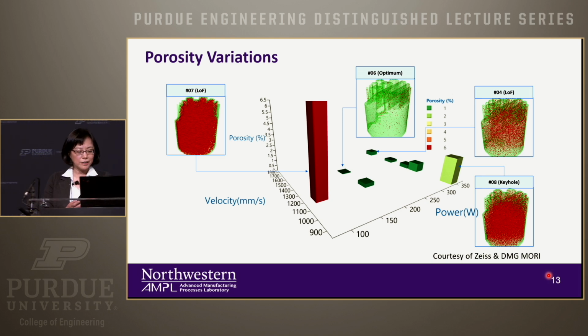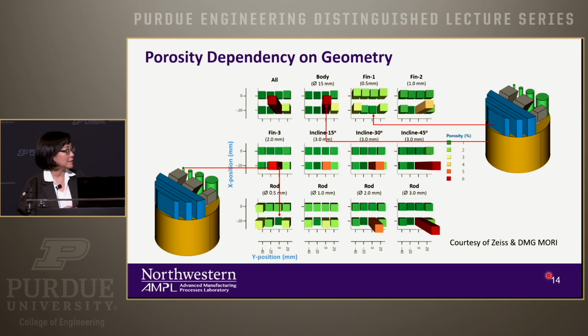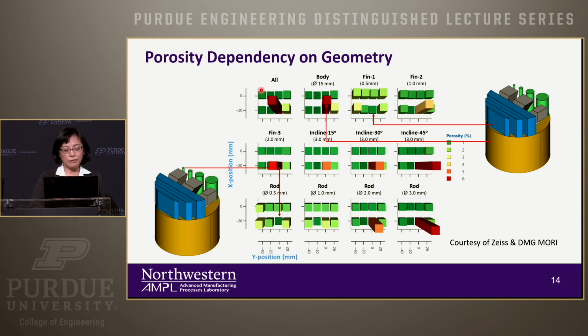However, if you do a little bit more careful analysis, which is this one, they have 8 pairs of power and velocity. So for every same position, it's the same process parameter. What's different is that in each block here, everything is counted the same, just counted all together. These are the porosities. If you just count the body here, the yellow ones, and these are the porosities.